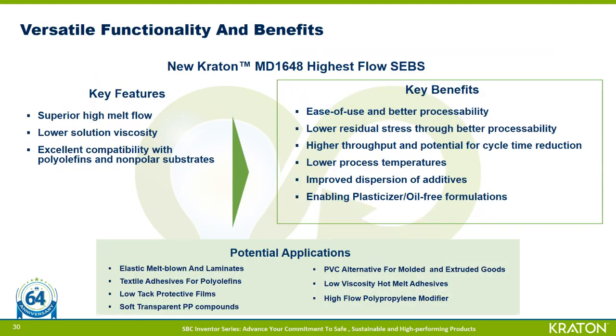Kraton MD1648 is another new molecule in the SEBS family. This grade has very low viscosity and a high melt flow and has excellent compatibility with polyolefins and non-polar substrates. So because it has such a low viscosity, it may also be of particular interest to formulators. So here, the low viscosity and high melt flow may enable easier processing and the potential to reduce cycle times and generate additional formulation flexibility, particularly around VOC content.